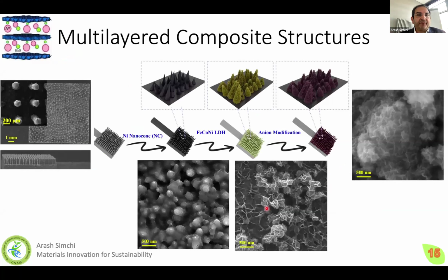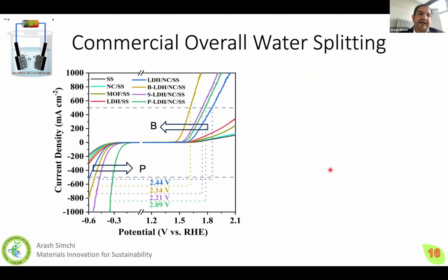We went to the laboratory, we produced these layered double hydroxide materials on the surface of our structured electrodes, functionalized and anion modified them. And the point is to have a good interface. We also deposited nickel nanocones to increase the surface area and better match between the metal substrate and the ceramic material. As you see here, some SEM pictures. The good point is we tested it and you see current density versus potential for hydrogen production for different materials.